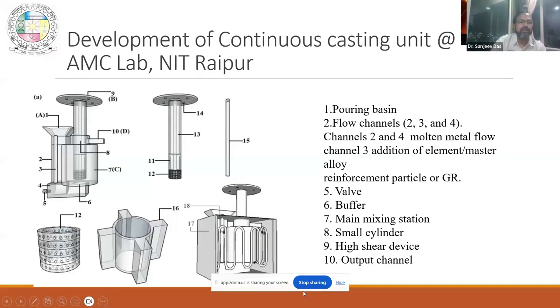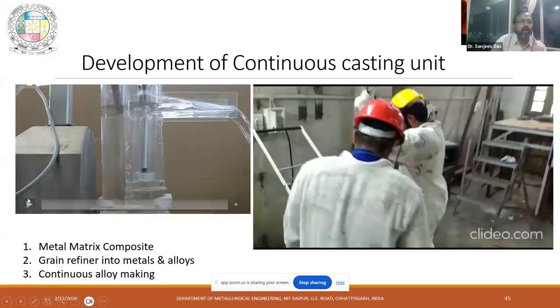Now what is this design? This design is basically we have a mixing chamber, we have the rotor stator device. Now instead of pouring the liquid metal from the top, we are pouring from the side, and it is going below this chamber and coming out from this baffle, and then it is hitting the rotor stator device, and it starts mixing. Now when the rotor stator works, there is no vortex formation at the top, so any contamination at the top is not coming in. So this is the idea we came up with, and we made an insulation because all the liquid metal will go there, so we have completely insulated it with heaters and all, so the metal stays in the liquid condition. I will show you some videos that will clear the idea about it.